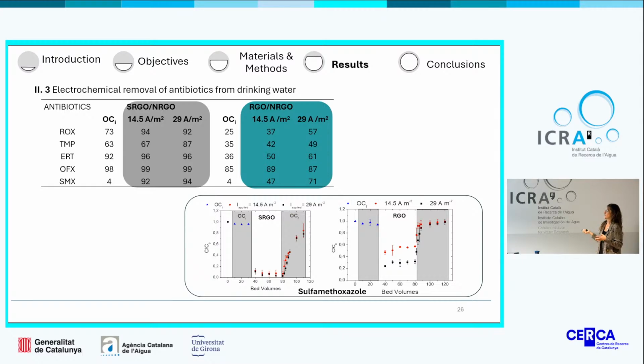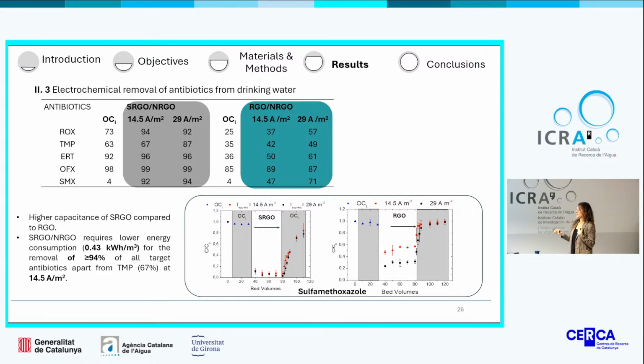With the application of current, it was kind of the same tendency. According to this, we could observe that even at the lowest conductivity, an important removal of all antibiotics was observed in the case of SRGO and RGO. Comparing sulfamethoxazole, which was limitedly absorbed by RGO and completely absorbed by SRGO, we could observe something really interesting. In the case of SRGO, sulfamethoxazole needs more time to reach the initial conditions, compared with the RGO electrode. This is probably a consequence of an enhancement of the capacitance of our electrodes. So we can say that SRGO and RGO require lower energy consumption for the removal of more than 94% of all target antibiotics except for trimethoprim at the lowest current application.